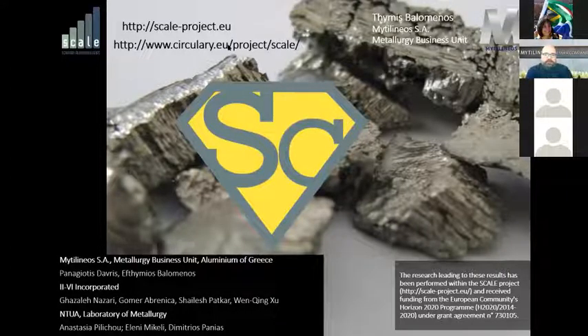Again, I think we have one from Nikhil Dawan as well. Do you think acid baking can facilitate the structure breakdown of bauxite residue phases to facilitate extraction? Yes, definitely can. I've seen two types: there is the acid baking, and there is also another technique performed in Germany, in Aachen, which is sort of pulp leaching. I've seen it also mentioned as water deprived leaching, where you add a lot of acid with very little water, and you raise the temperature to a point where the water basically evaporates. Both of these techniques break down the structure, and you're able then to leach out the rare earths.